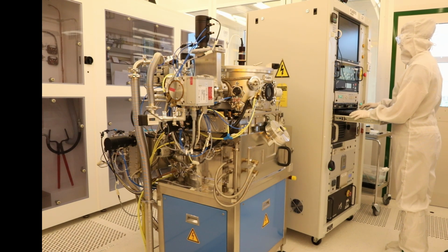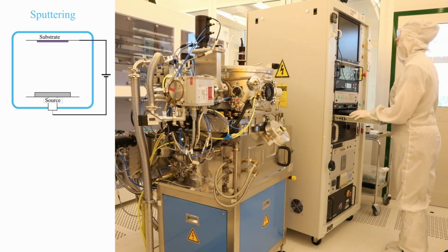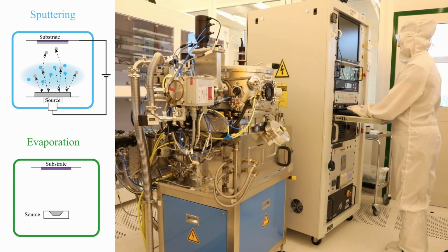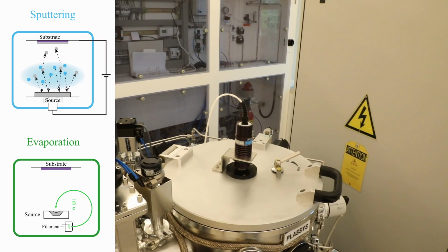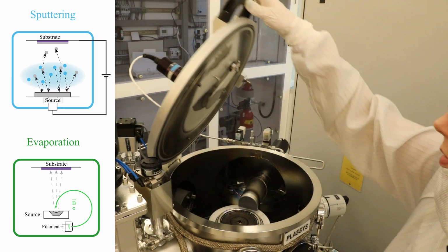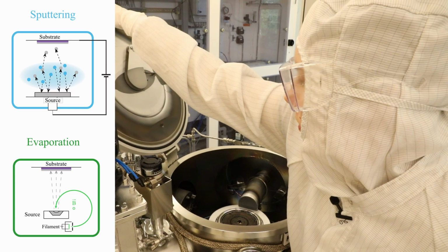In this step, we will deposit the aluminium by evaporation instead of sputtering, which is slightly different. In sputtering, we dislodge the atoms from the material source by plasma ion bombardment. In evaporation, the metal source is heated up by, for example, an electron beam, so much so that the metal melts and evaporates, and the vapor of this metal then condenses on the substrate.